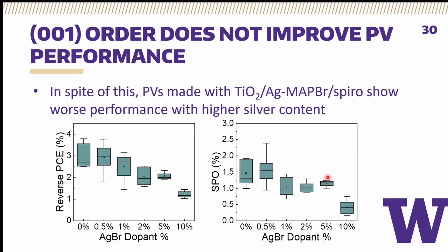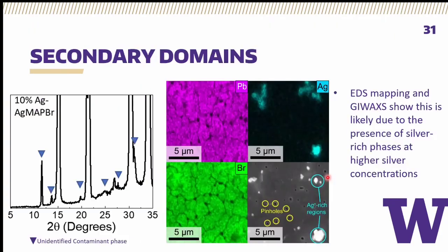Sadly, this does not lead to better devices. In fact, it led to much worse devices. But this is not due to the increased order of our film, but rather due to the emergence above 1% silver incorporation of these unfortunate secondary phases. The benefit of silver not incorporating into the bulk of your crystal is that you can get this segregation that induces this order, but the unfortunate consequence is that you have these secondary phases that emerge as well.